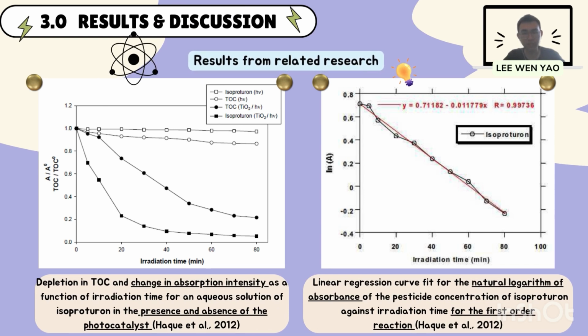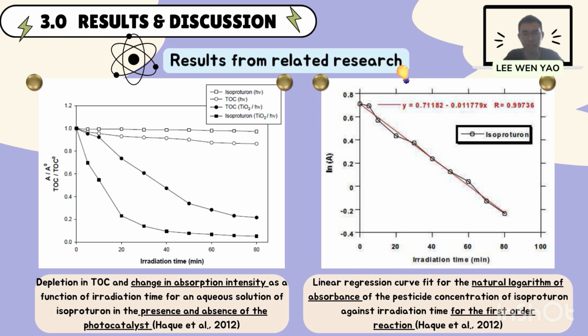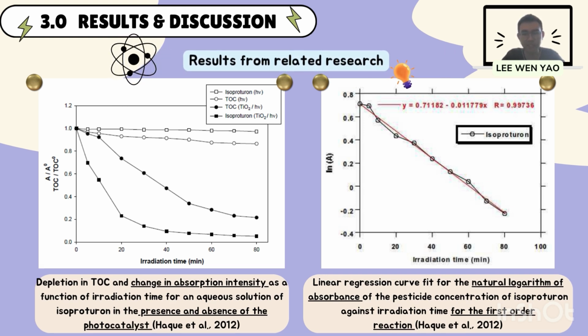This page shows the graph obtained from the titanium dioxide photocatalytic degradation investigated by Haque and others in 2012. Without a doubt, the efficiency for photocatalysis of organic pollutants was increased enormously with the addition of titanium dioxide, as indicated by the decrease in absorption intensity and depletion in total organic carbon content as shown in the left graph. Other than that, the mineralization and decomposition rate can be fitted in an exponential decay curve that suggests both reactions follow first order reaction and their rates were able to be calculated precisely.